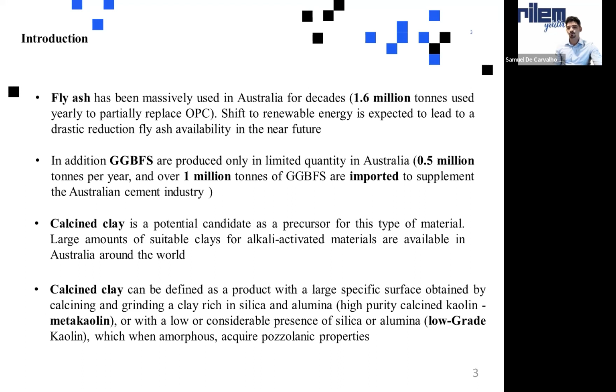Commercially, you know this material as metakaolin, but it's very important to define it. When I'm talking about metakaolin and calcined clay here, I'm talking about the content of kaolinite in the material. When the material has a low concentration of kaolinite, you call this calcined clay, sometimes low-grade calcined clay or low-grade metakaolin. When I'm talking about metakaolin, it's 95-100% purity of material.